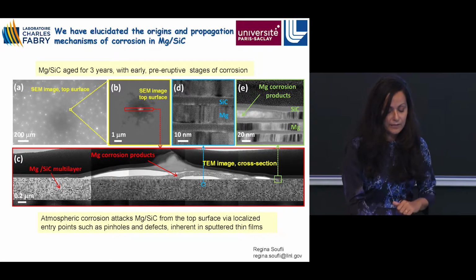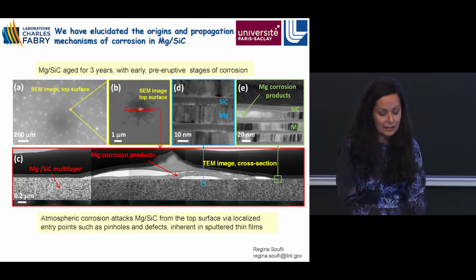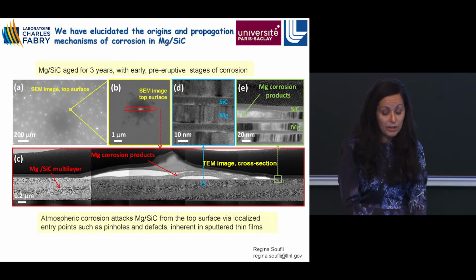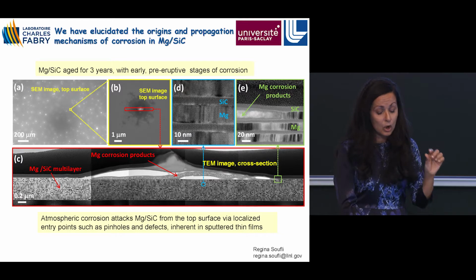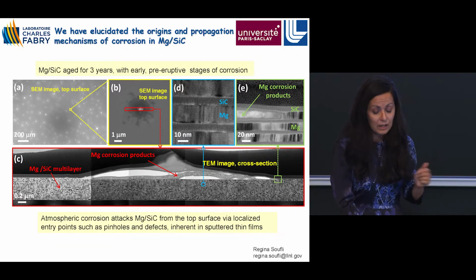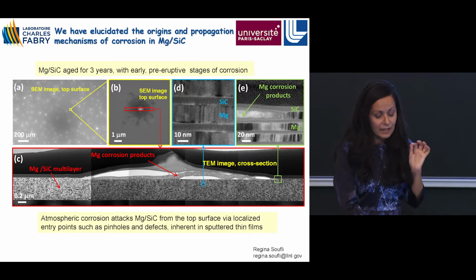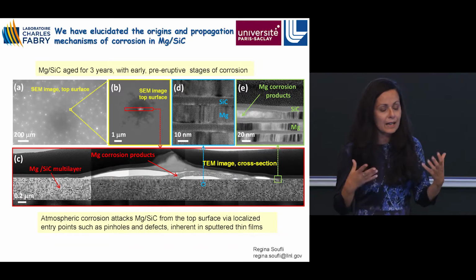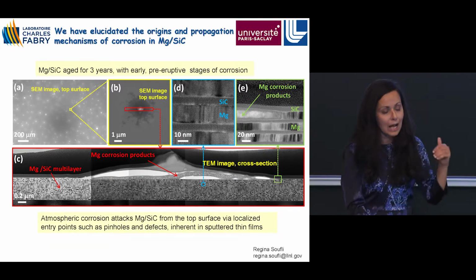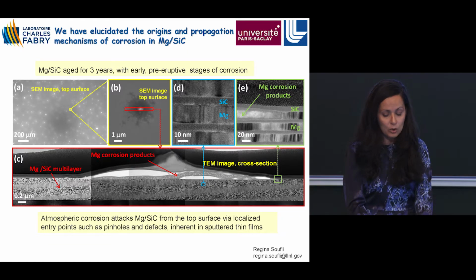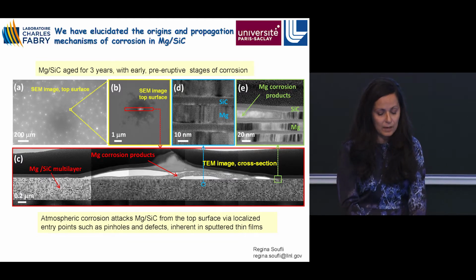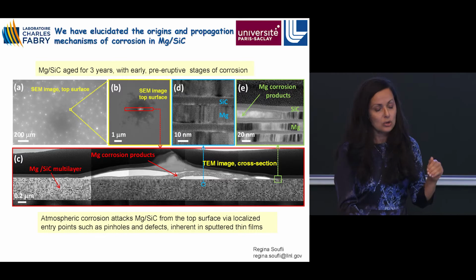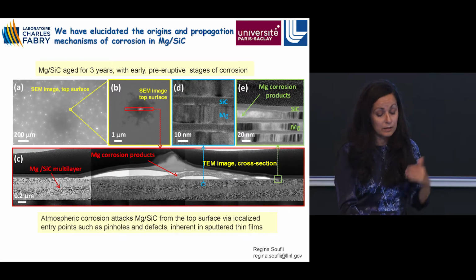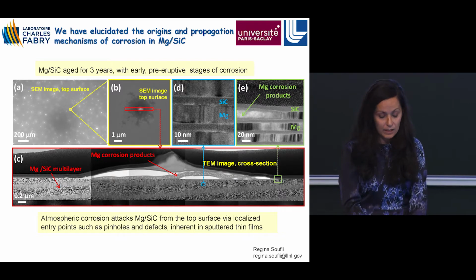We determined via this characterization that atmospheric corrosion attacks the coating from the top surface. The top surface has a silicon carbide capping layer, but it is not enough to protect because it has to be thin to preserve the high reflectivity, about 100 nanometers, let's say. At the same time, this top layer has defects and pinholes which are inherent in these coatings. So aggressive ions in the atmosphere, like chlorine and hydroxyl, attack the coating from the top surface and start forming corrosion products. You can see here the corrosion product in the magnesium layer. Once they attack the first magnesium layer, this effect propagates in the layers underneath, and you basically end up having these catastrophic effects.